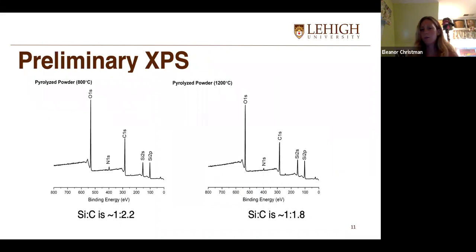And so I was able to do XPS on these powders. I'm still actually waiting on the 1000 degrees Celsius powder because that was sent out this week. So I don't have that finished yet, but here's the 800 and 1200. And it's interesting to note that the silicon to carbon ratio is increasing. So you can see that the amount of free carbon in these samples decreases as the pyrolysis temperature increases, which is what we had hypothesized.